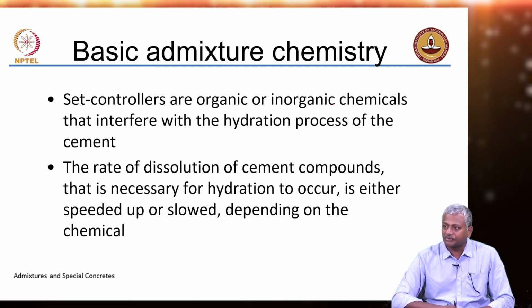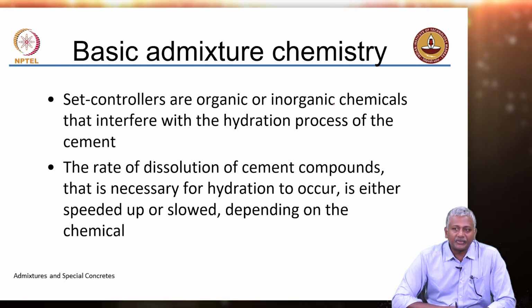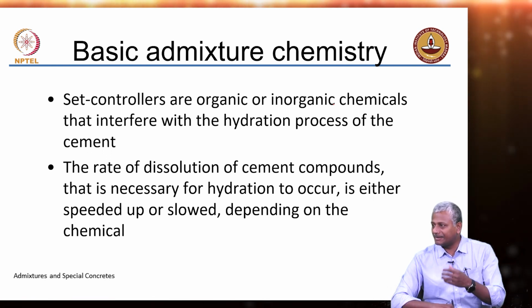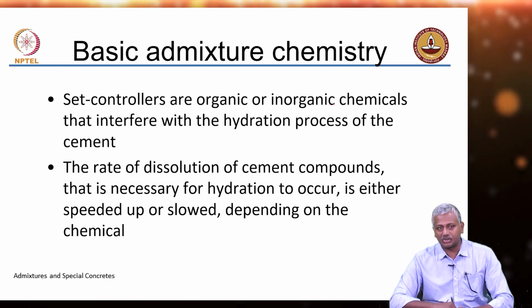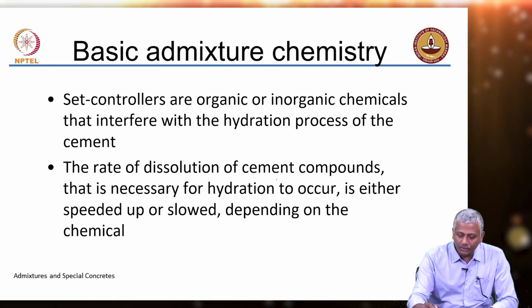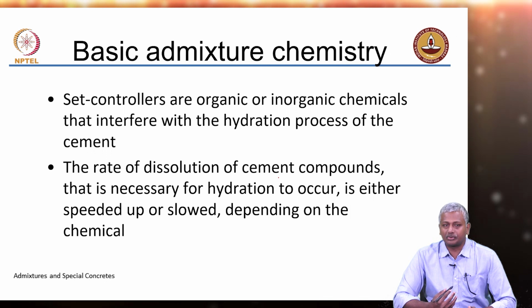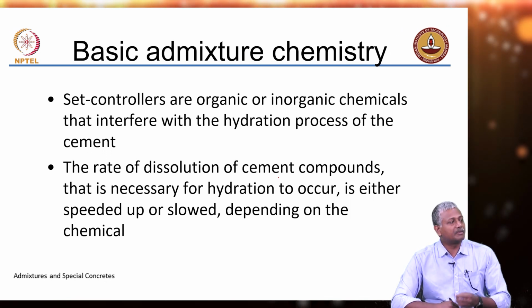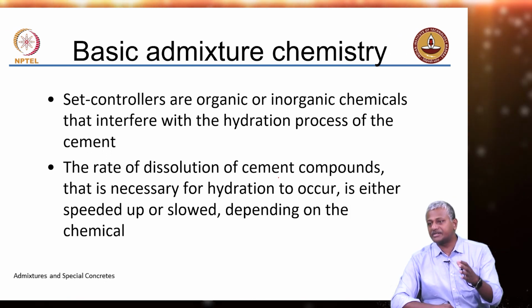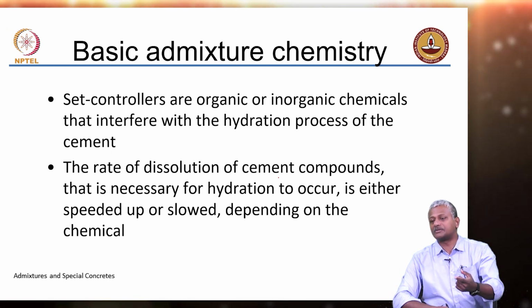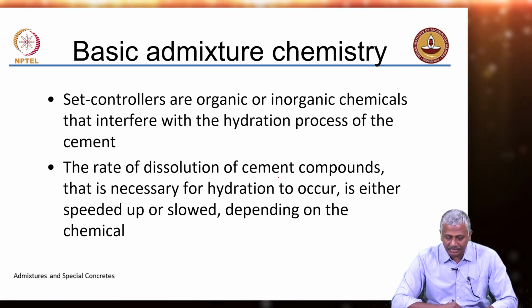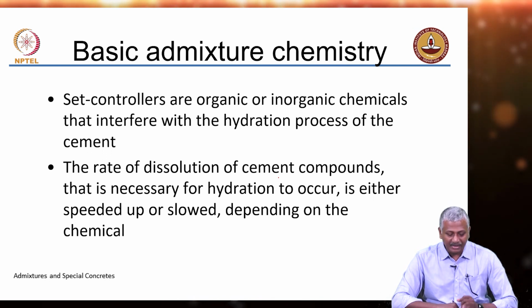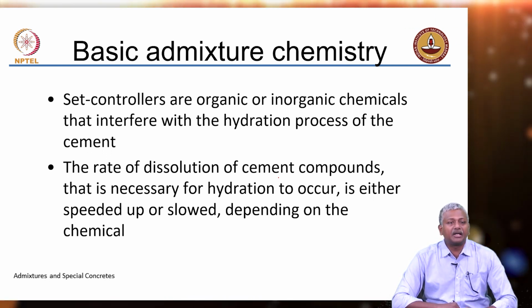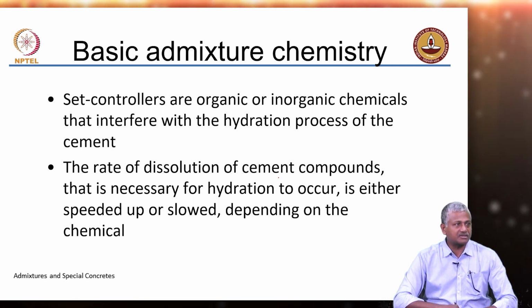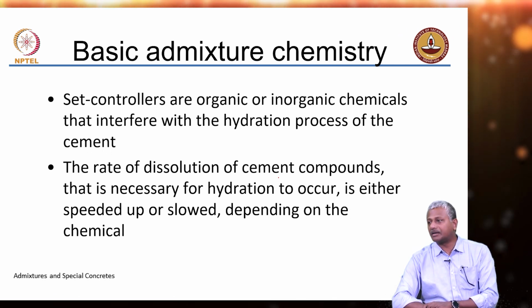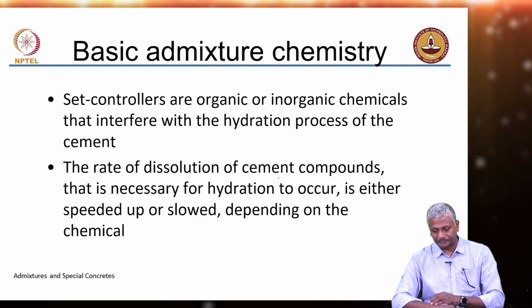But in the case of these chemicals, we have almost a direct involvement in the way that the reactions actually happen. Okay. So, the rate of dissolution of cement compounds that is necessary for hydration to occur, as we discussed earlier, the compounds of cement first lead to a dissolution and reprecipitation to really start forming your hydration products. So, this rate of dissolution is either speeded up or slowed depending upon the chemical that you use. So, an accelerator will speed up the dissolution, a retarder will slow down the dissolution.